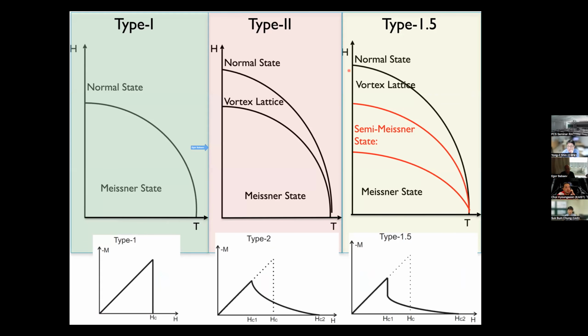So basically, as a phase diagram of a superconductor, if you move away from this simple one-component model, it has not just the normal state, vortex states, and Meissner state, but it also allows phase coexistence, microscopic phase separation between the vortex clusters and Meissner domains.